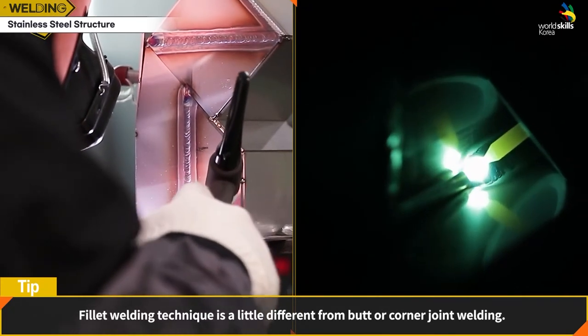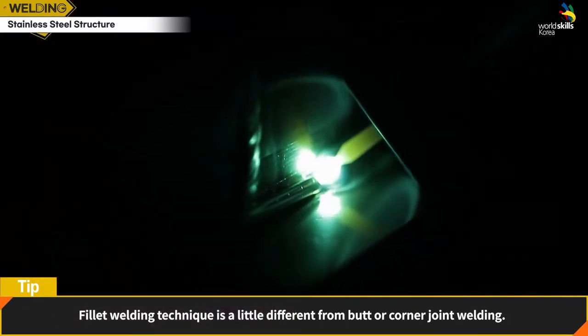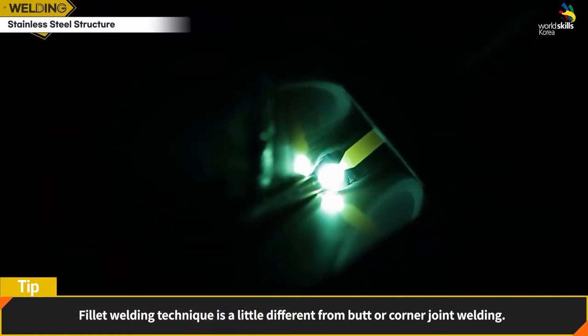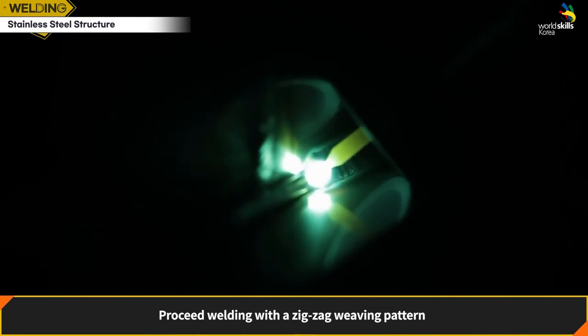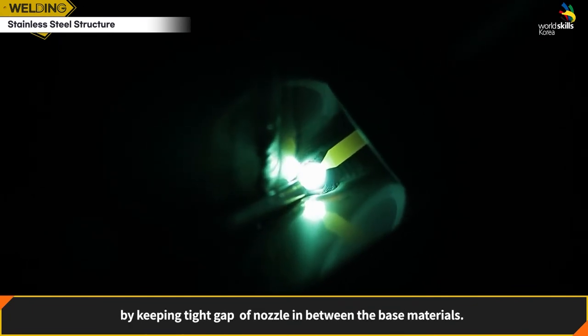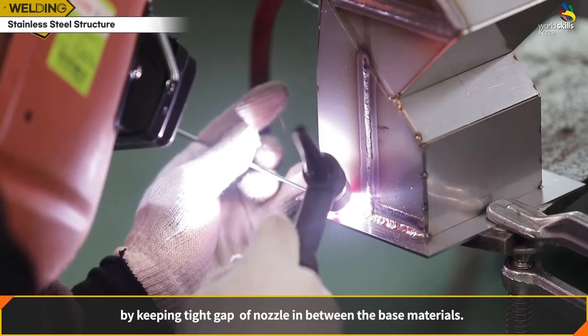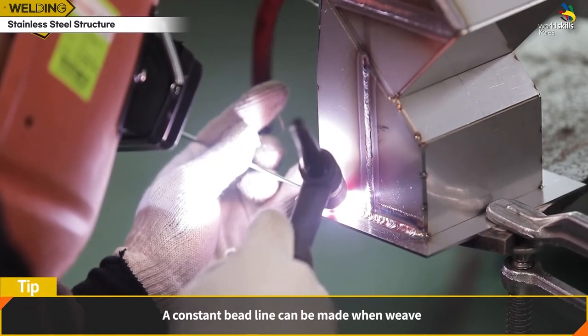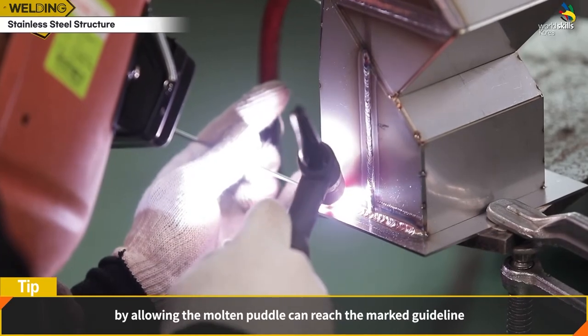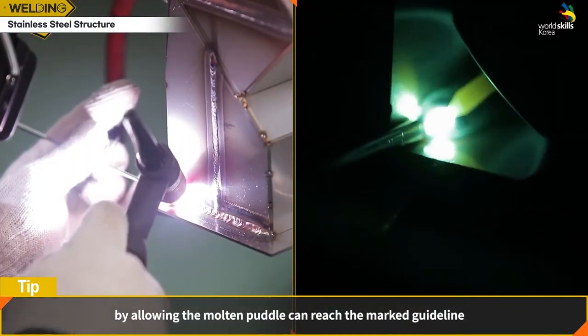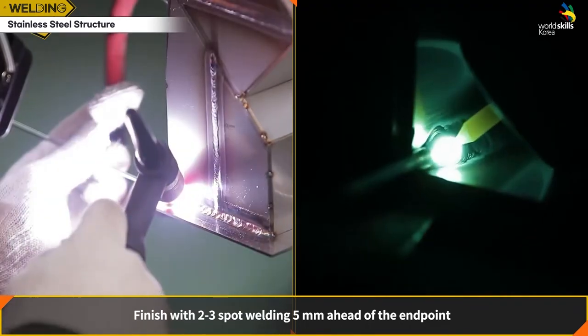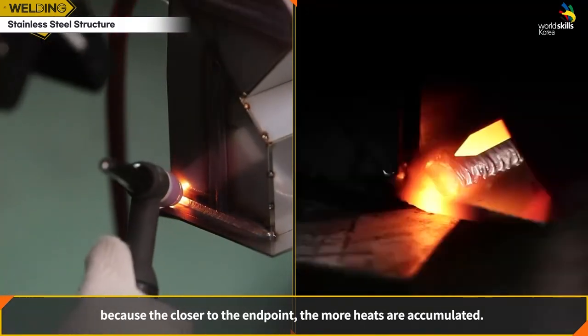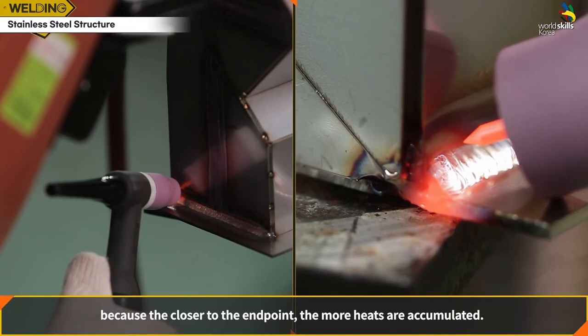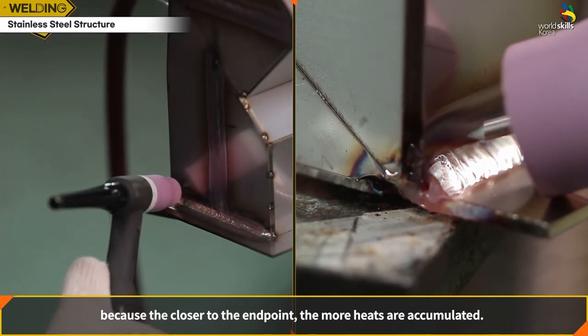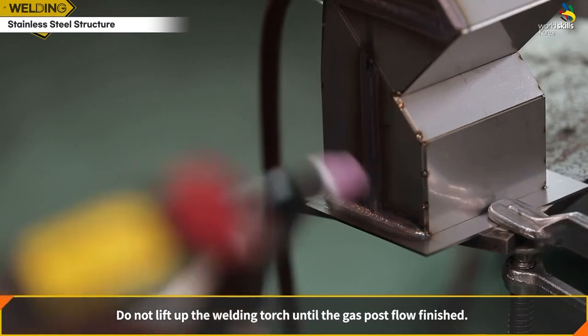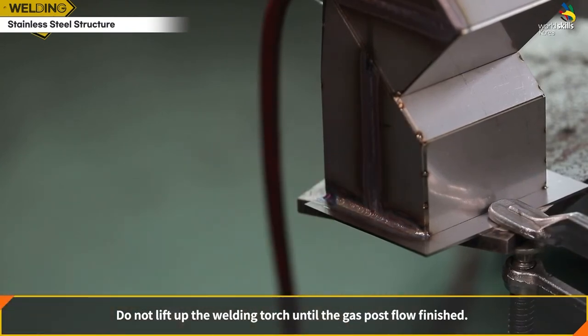Fillet welding technique is a little different from butt or corner joint welding. Proceed with welding in a zigzag weaving pattern, keeping a tight gap between the nozzle and the base materials. A constant bead line can be made when weaving by allowing the molten puddle to reach the marked guideline. Finish with 2 or 3 spot welds 5 mm ahead of the endpoint, because the closer to the endpoint, the more heat is accumulated. Do not lift up the welding torch until the gas post flow has finished.